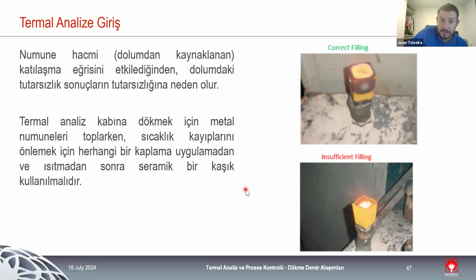I don't know if it is the case in this example, but if this is not possible, what I can say is that you could try to take the sample from the treatment ladle, and you can try to add the amount of inoculant corresponding to the volume of the cup. And I cannot give you values here because I don't know the volume that we are dealing with and the amount of inoculation that we are dealing with.